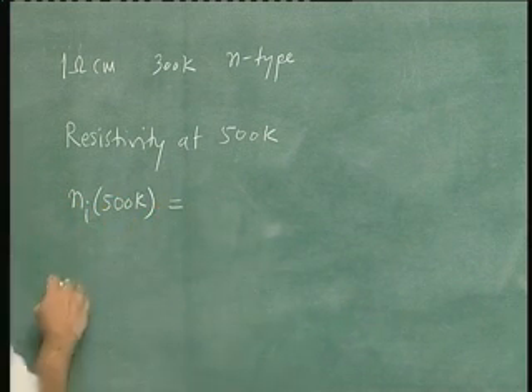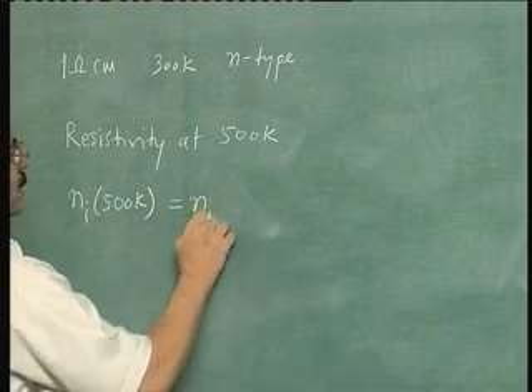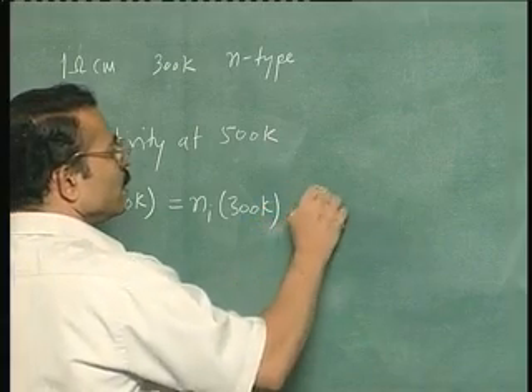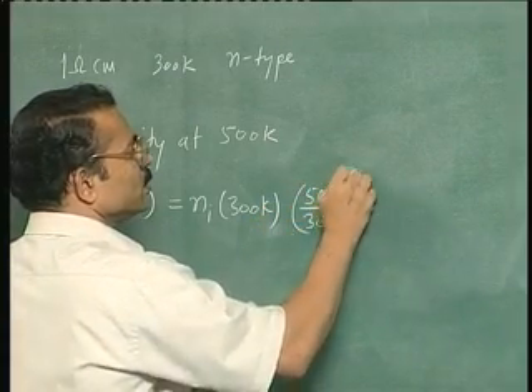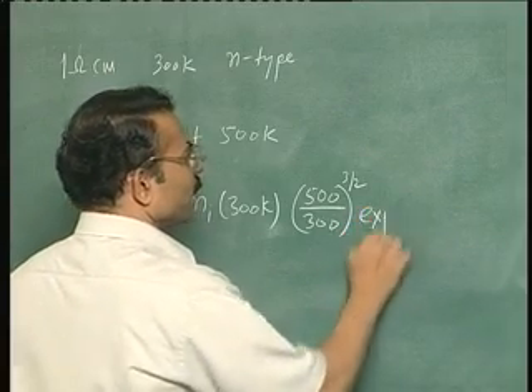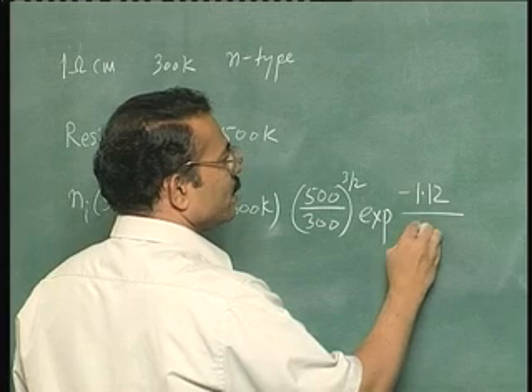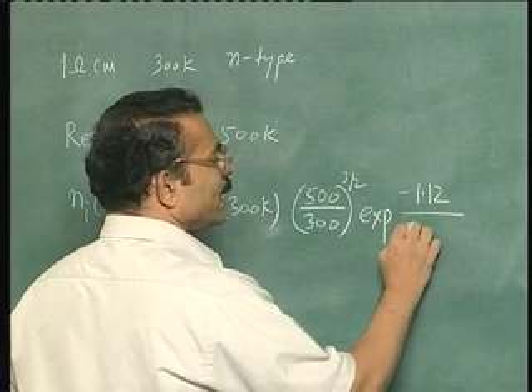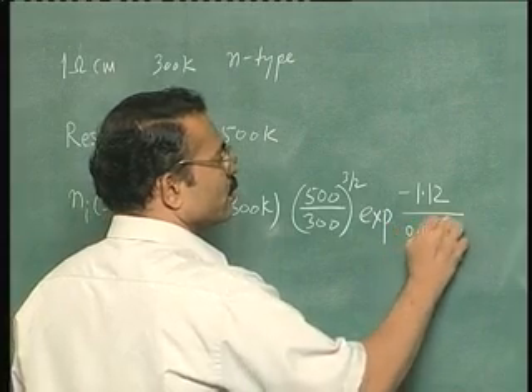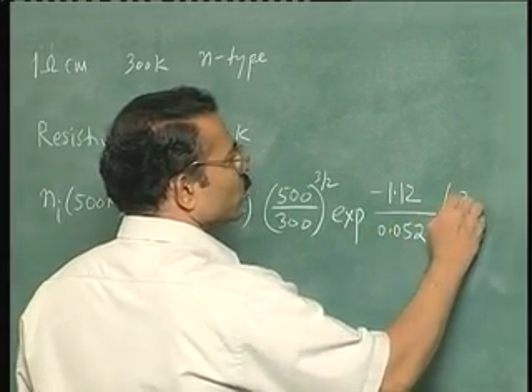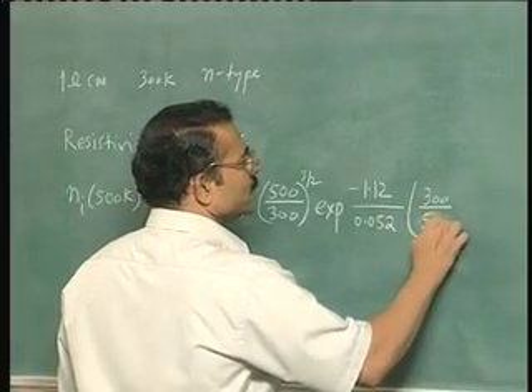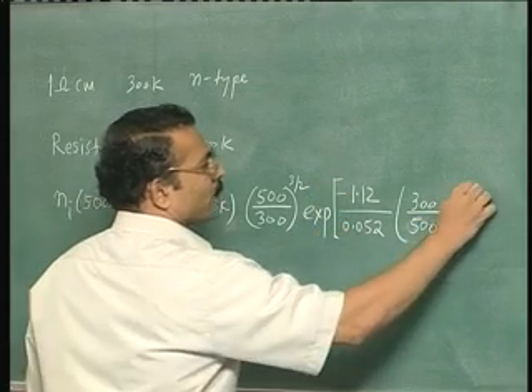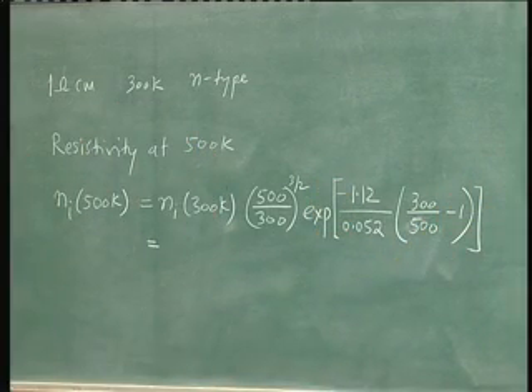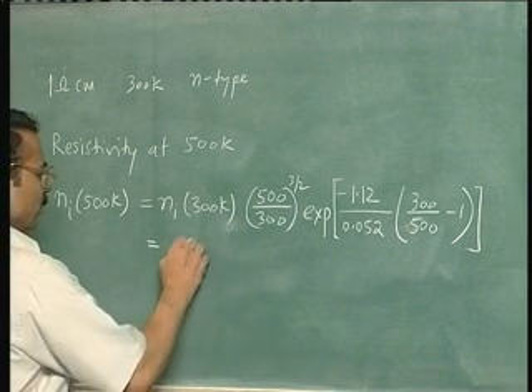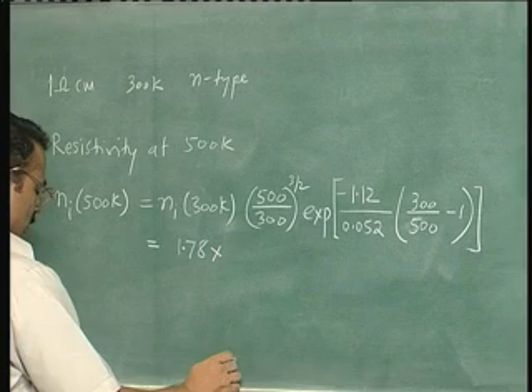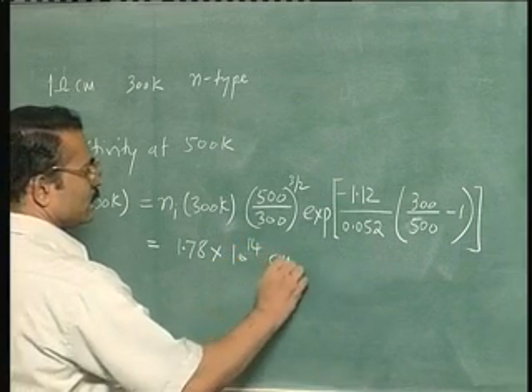Now this we can find out very easily, as we had done earlier in this course. You can write this in terms of Ni at 300 K into (500 upon 300) whole power 3 by 2 into exponential of minus 1.12, which is the energy gap, divided by 2 times k, where T is the room temperature, that is 0.052, into (the room temperature, which is 300, by the temperature of interest, that is 500, minus 1). Okay. So you make this calculation and you will get the result as 1.78 into 10 power 14 per centimeter cube.